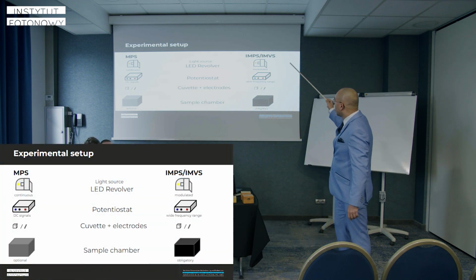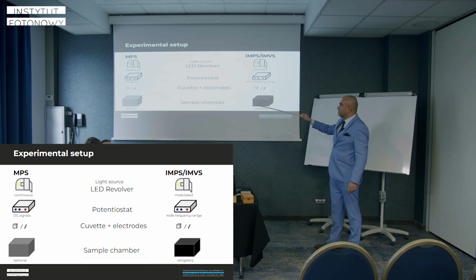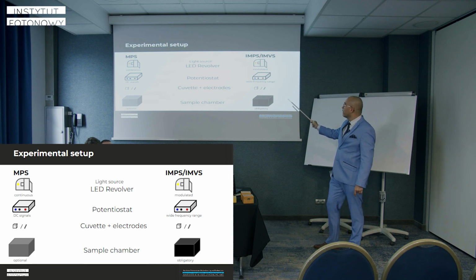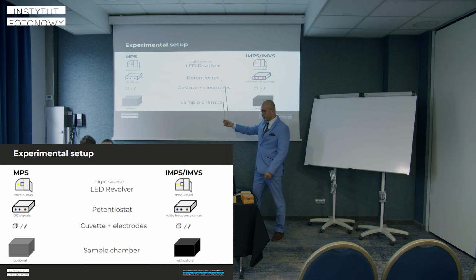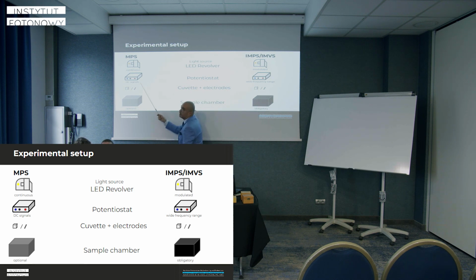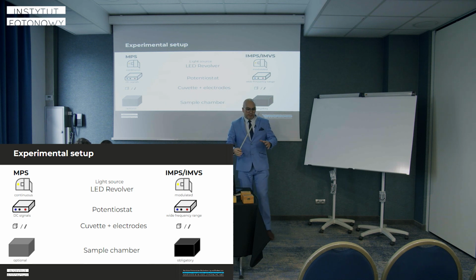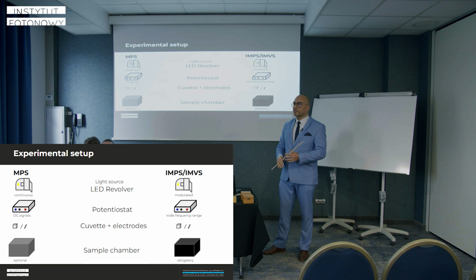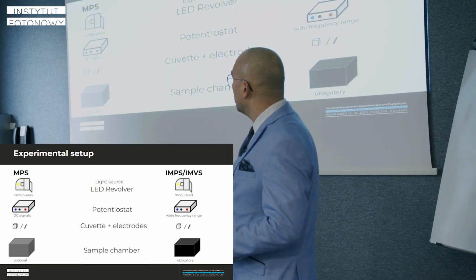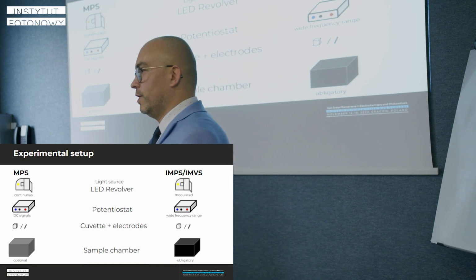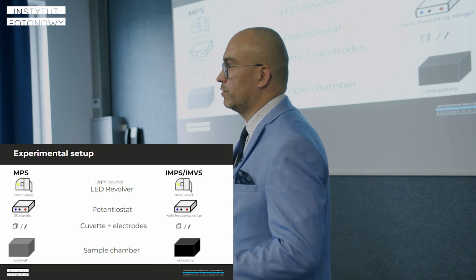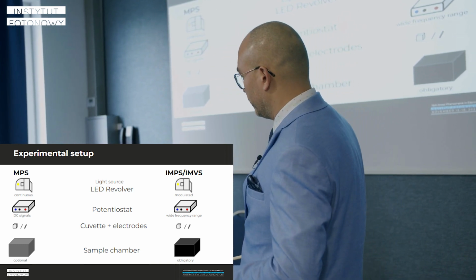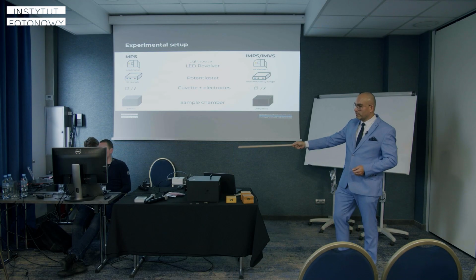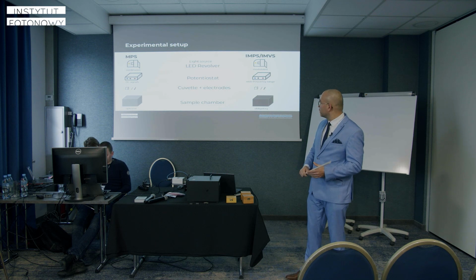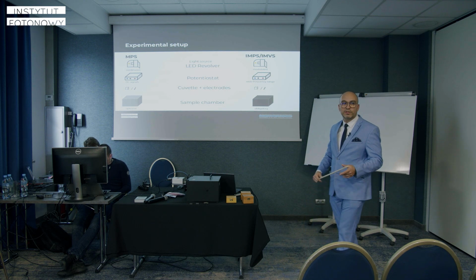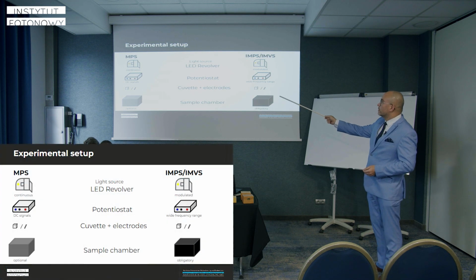This is because we measure here alternating signals in a wide frequency range, and these two setups are configured in a different way. Here we only measure stationary signals, so the setup is configured to be not sensitive to AC signals, and then we have to take care to screen the sample or just cover it with a box to protect from external light. But in this case, we need a Faraday cage to screen off all stray fields and electromagnetic noise and so on. And of course, a cuvette.